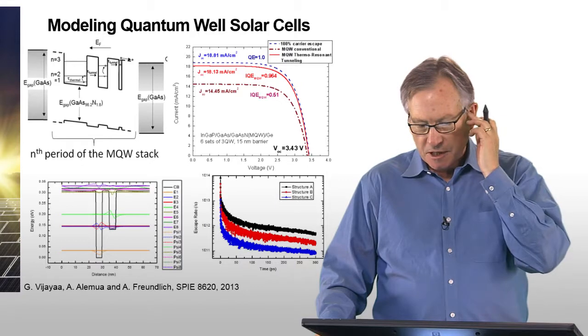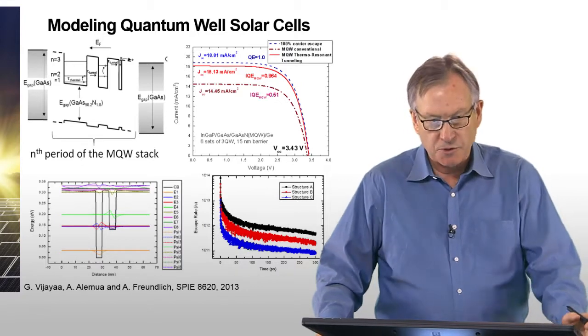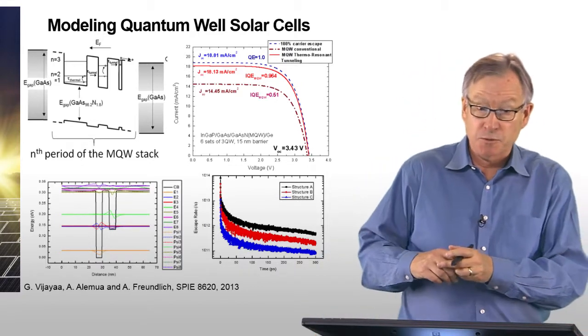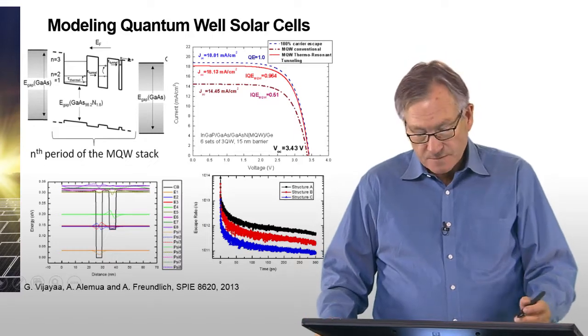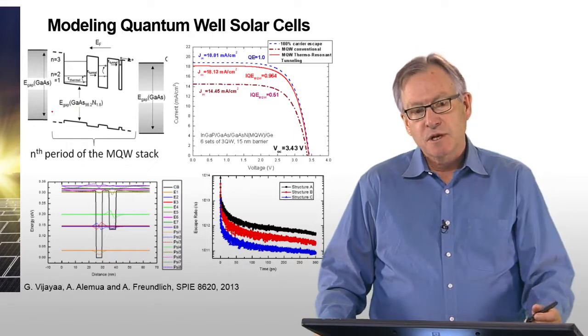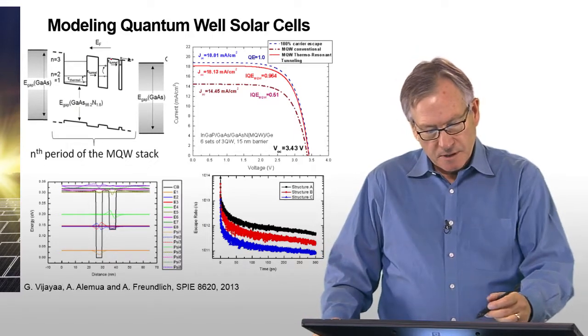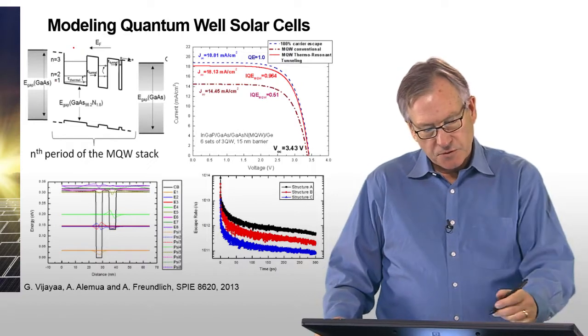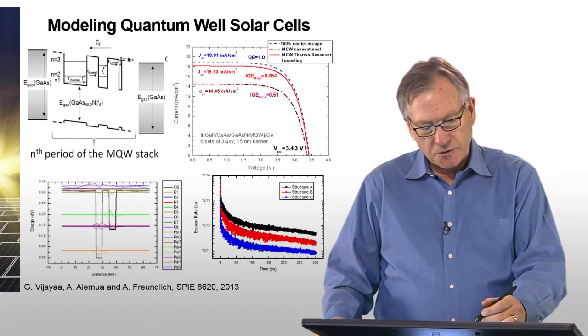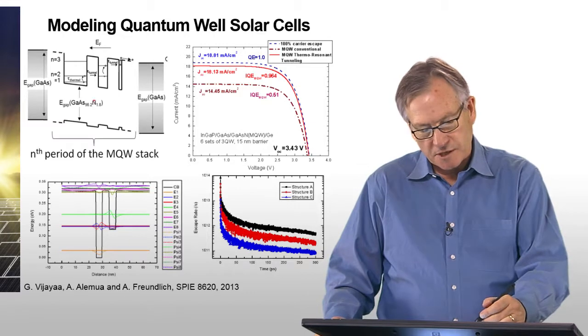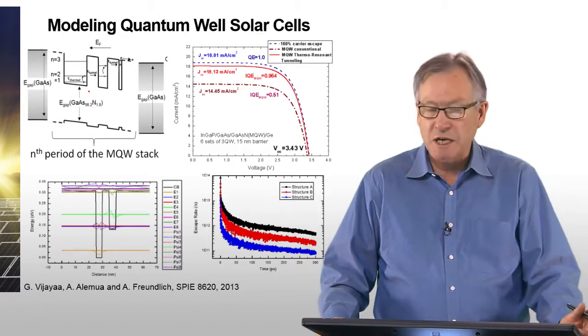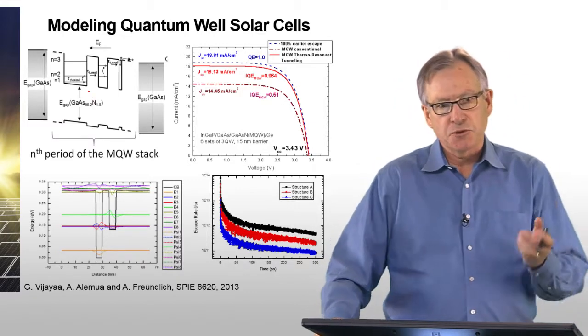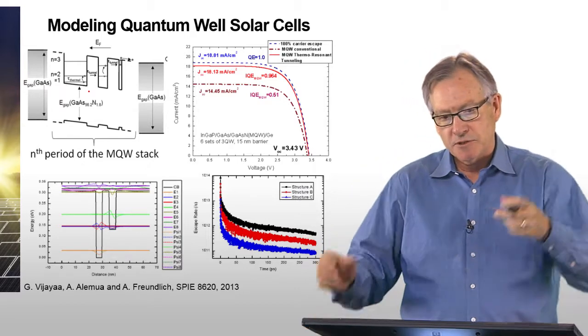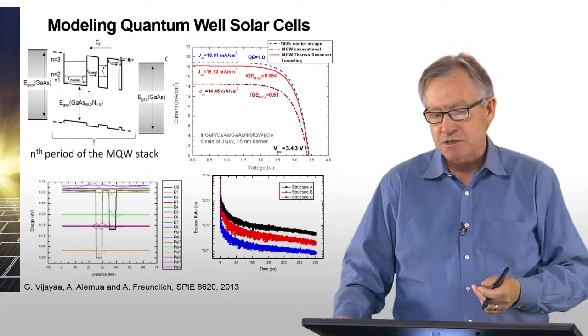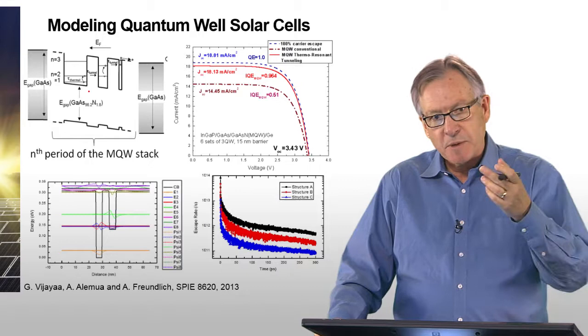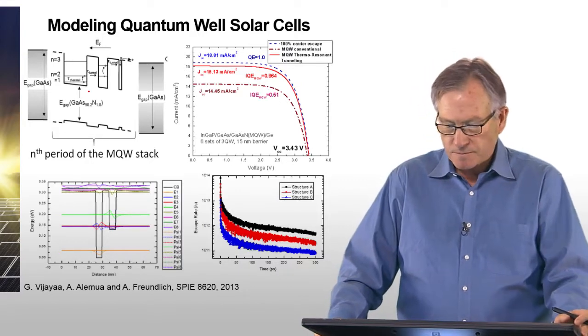So some of the modeling that we're involved with, in partnership with the University of Houston, Alex Freundlich's group there, is looking at, first of all, the electronic structure of these wells using new materials. Instead of using gallium arsenide, using what's called the dilute nitride material, gallium arsenide and a small quantity of nitrogen, which allows you to tune both the band gap and the lattice constant so that you can get better lattice matching during epitaxial growth.